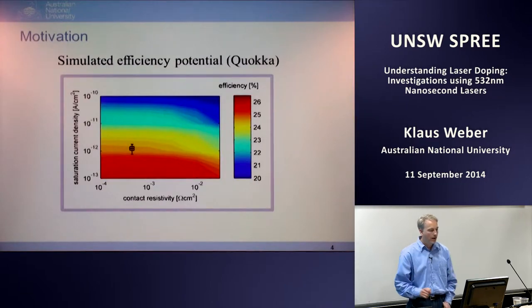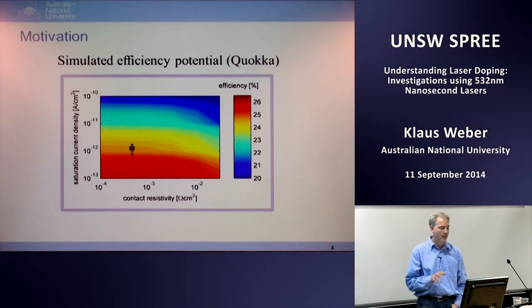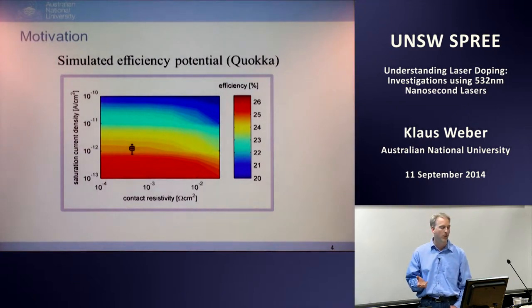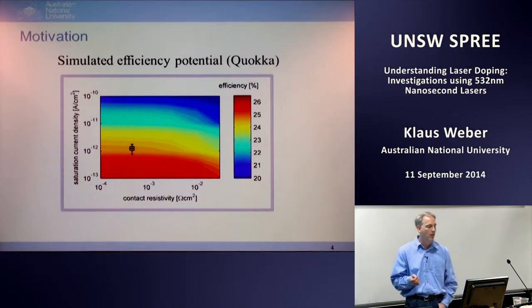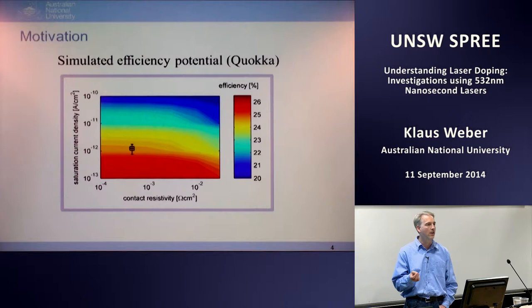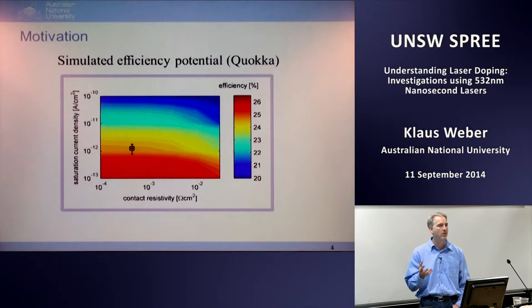So once again, I've lifted this one from Andreas's presentation. This really summarizes where you can get to if things go right. What it comes down to with these IBC cell concepts is that, in terms of the laser doped regions, there are two parameters that really matter. One of them is the contact resistivity, and the other is the saturation current density of these laser doped regions. So in this simulation, the spacing of the contacts has been optimized for each one